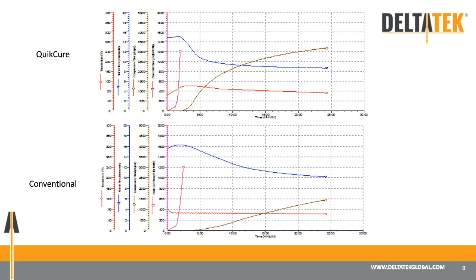And the bottom chart that we can see there actually has an indication that at 16 hours, there should be nearly 1,000 psi of compressive strength in that slurry. This is actually a slurry which was pumped and not subject to the quick cure heat sweep. And we can see from this video that at 16 hours, the slurry at mudline was not necessarily set. See if we can watch that again. As you can see, that slurry is still pretty liquid, so it's not always the case that it's set.